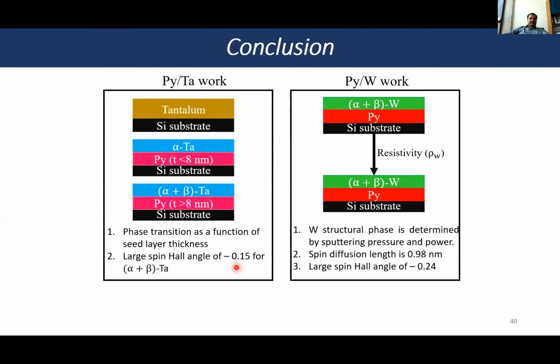So with this, I would like to conclude that in permalloy tantalum, we have shown that we can get a phase transition as a function of seed layer thickness, and a large spin Hall angle of 0.15 can be obtained. And in the case of the tungsten work, we can see that by changing the pressure and power, we are able to change the crystalline phase, and a spin Hall angle of 0.24 is reported from this work.